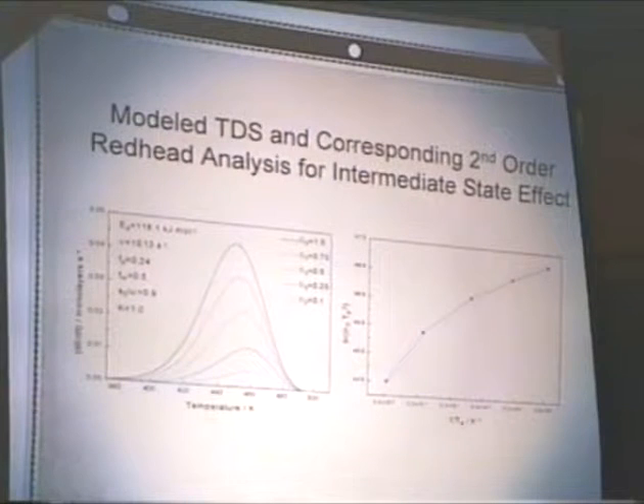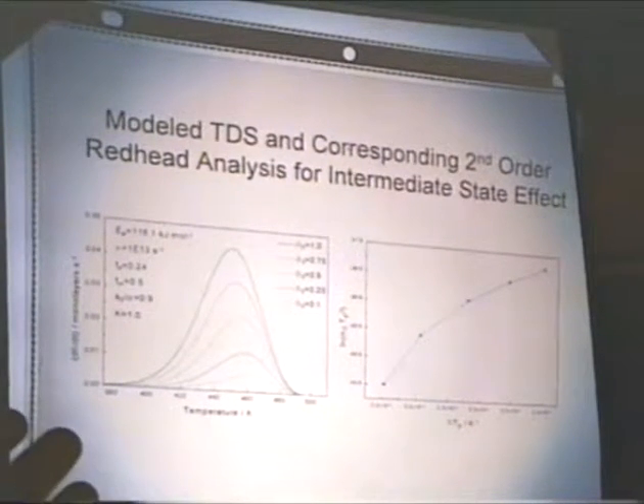If you see the corresponding second order analysis, it is not linear. However, it's less nonlinear than the coverage-dependent case, which indicates that perhaps we're on the right road to explaining this. But for now, we've not conclusively shown that it is indeed limited by desorption to a precursor state.